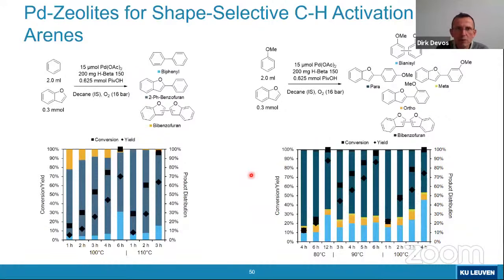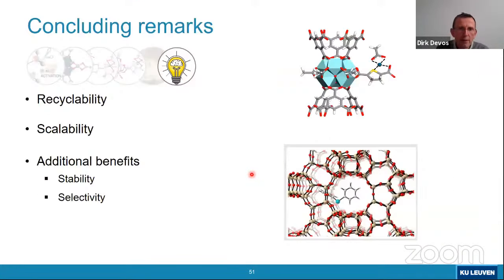Which brings me, it's more or less 6 o'clock, to my conclusion, namely that I hope that I have been able to convince you that with several heterogenized palladium systems, either on a MOF, as shown here, or in a zeolite, we can do something about the stability and the recyclability of the catalysts. We have scalable catalysts because, for instance, zeolite beta is a commodity. It's a material which is used on huge scale in petrochemistry. So that's really not a problem to do at large scale.